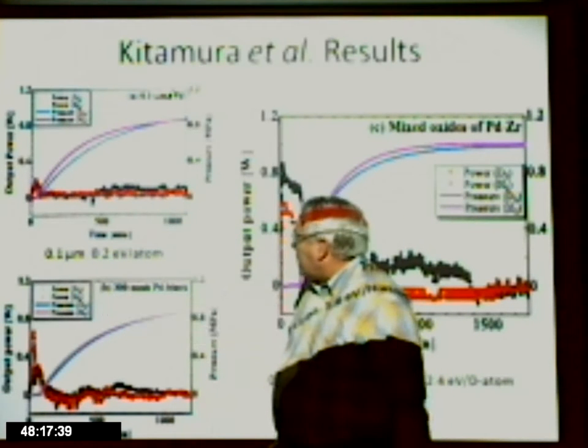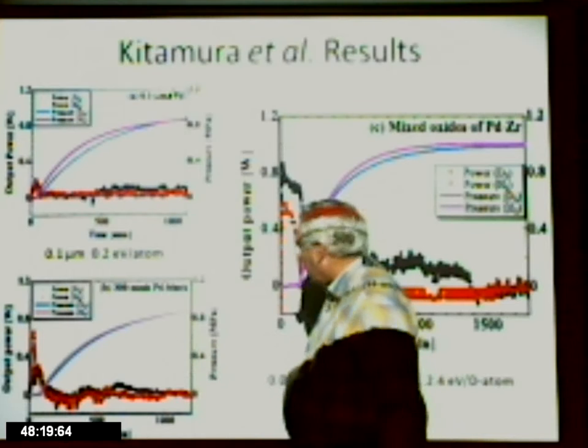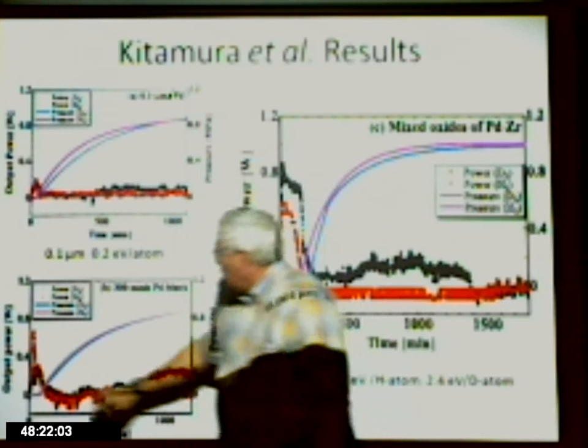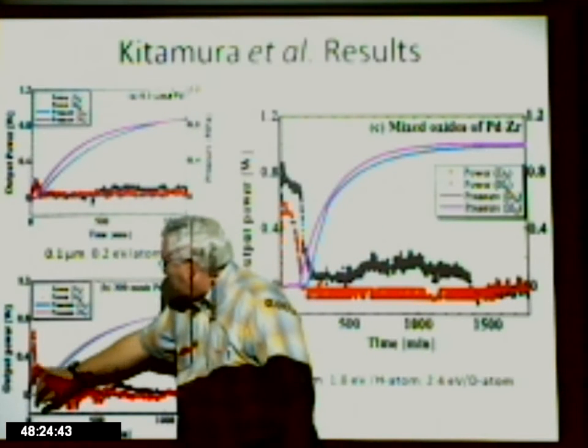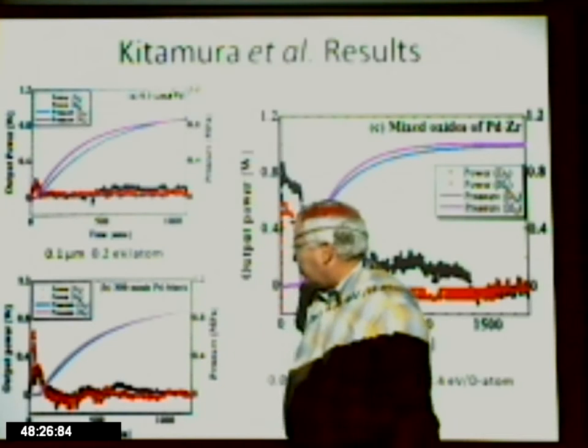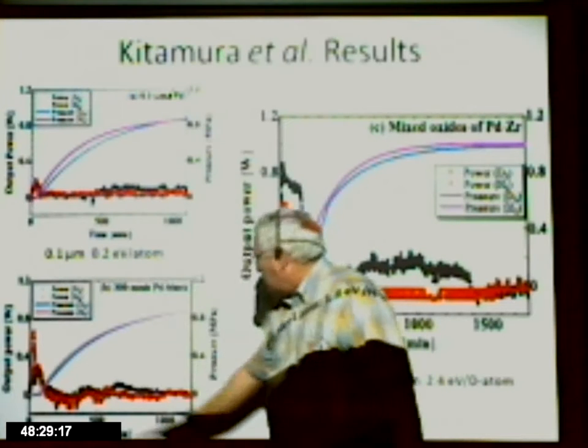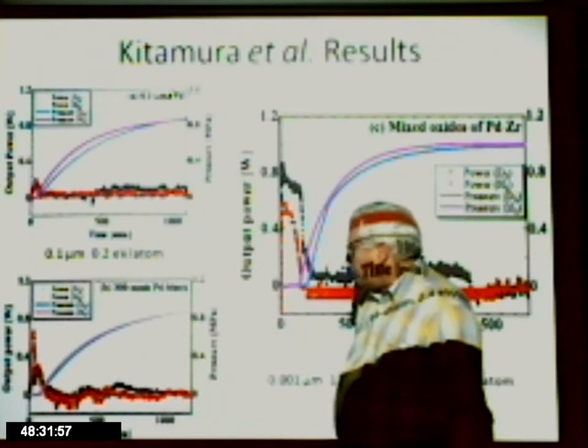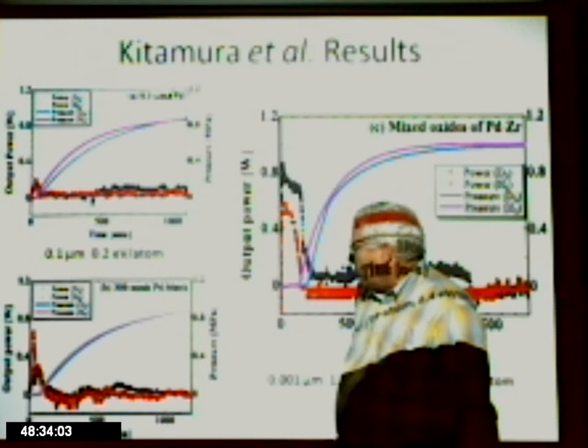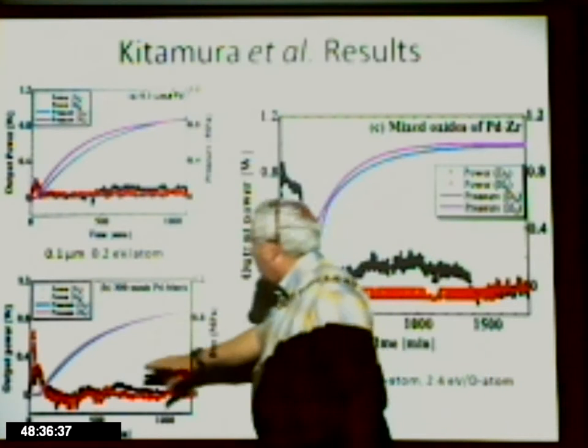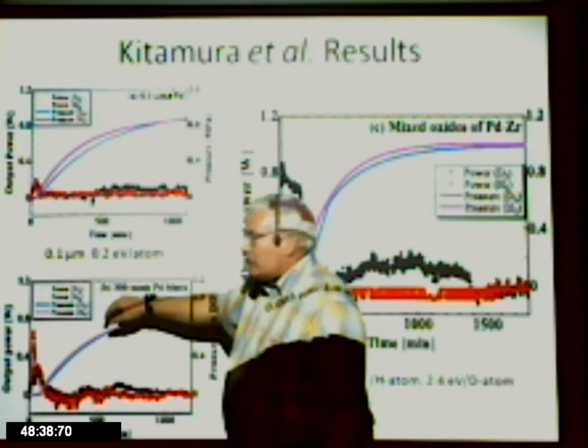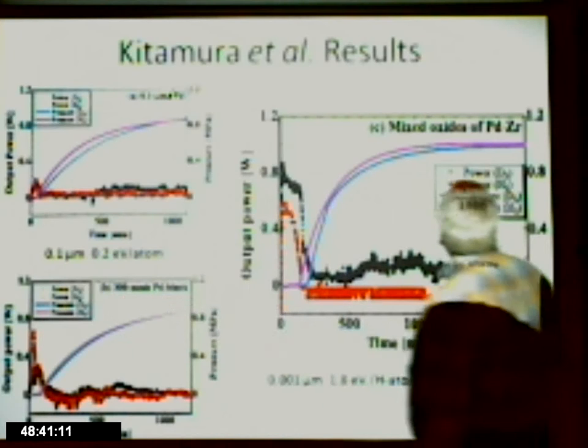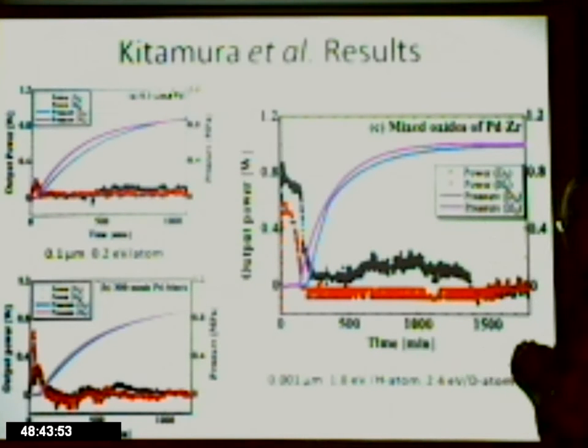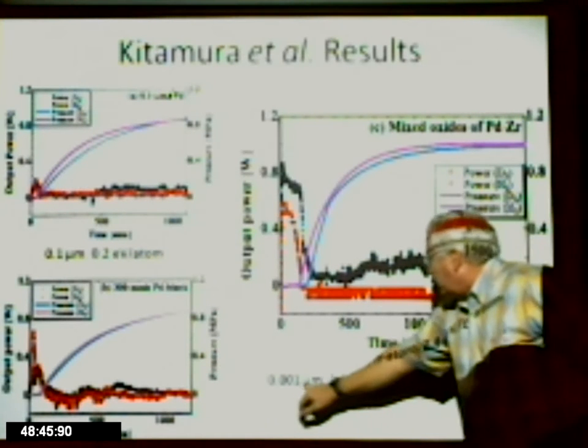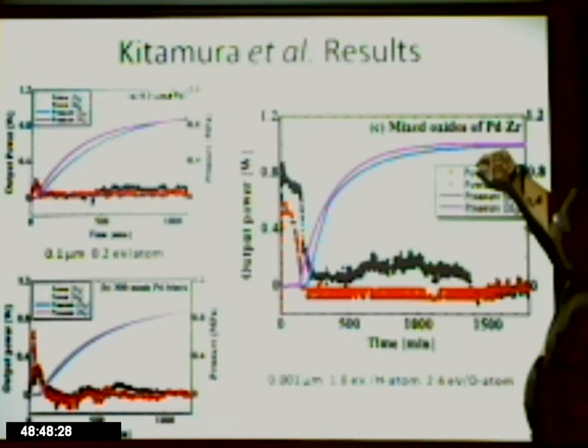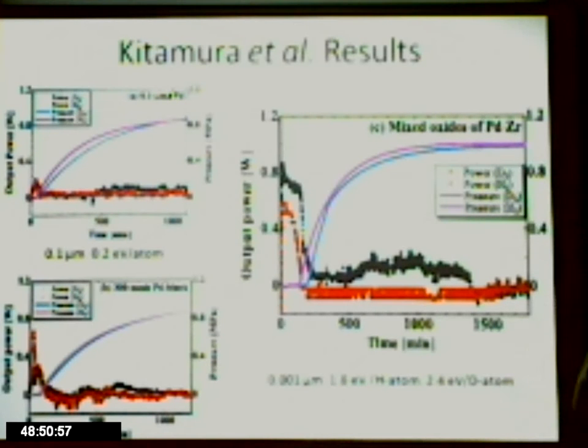300 mesh palladium black, these are much smaller particles. And in these particles, still statistically, there's close similarity between hydrogen and deuterium in terms of the heat of absorption. And both show no really characteristic excess power later on after they've been loaded. But this corresponds to a size of about 10 nanometers per particle. Now you go to 1 nanometer per particle, okay, about 0.001 micrometer per particle in this Pd zirconium nanoparticle process.